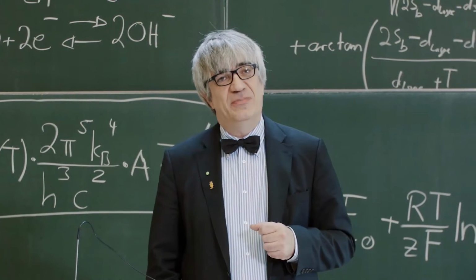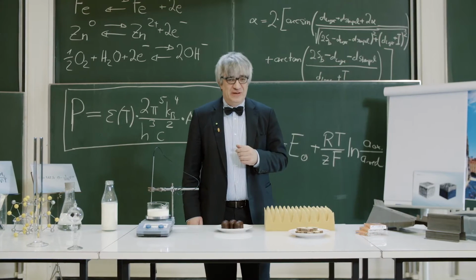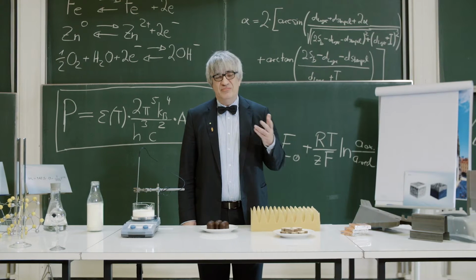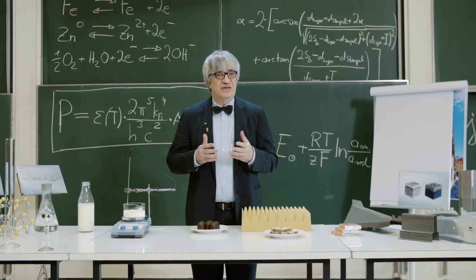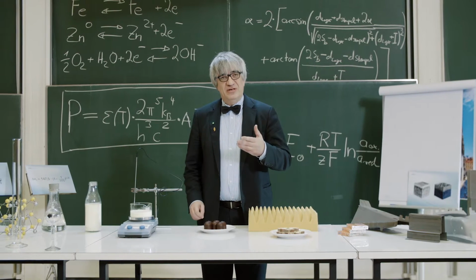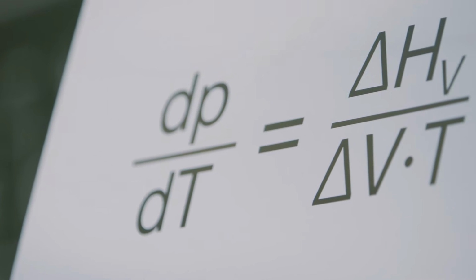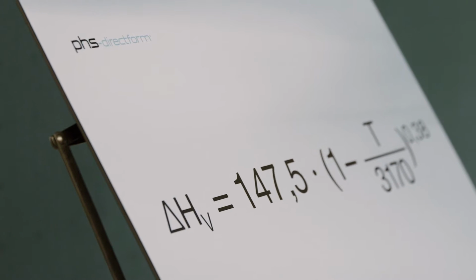The greatest secret of voestalpine's PHS technology is the zinc coating. Actually, at a temperature of 900 degrees during the PHS production process, the zinc should vaporize. This is prevented by a thin layer of aluminium oxide on the surface of the material. This layer doesn't allow the zinc to vaporize.